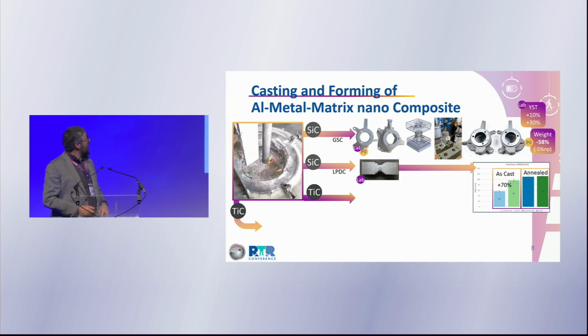Silicon carbide has also been used for low pressure die casting, just at lab scale. And here we can see something that was interesting and not expected at the beginning of the project. You can see in the as-cast condition we have two columns, which show the hardness of the material, and the as-cast with the nanoparticles is much harder. So the related mechanical performances are much higher. Once annealed, this difference is lost, because aluminum alloys are originally designed to refine the nanostructure through annealing.